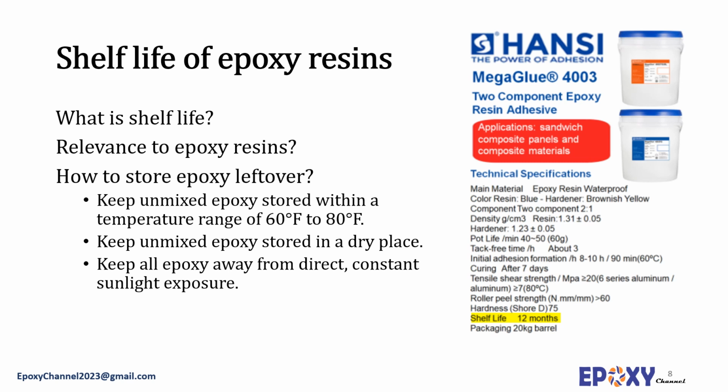Shelf life is defined as the length of time a product may be stored without becoming unsuitable for use or consumption. Shelf life depends on the degradation mechanism of the specific product. Epoxy resins and hardener formulations have a long shelf life compared to many polymers. The common shelf life for epoxy products is about 3 years for epoxies and 2 years for normal hardeners, and up to 6 months for reactive hardeners.